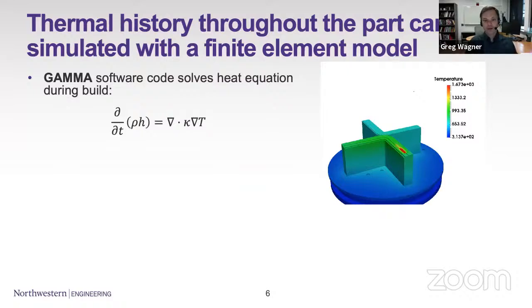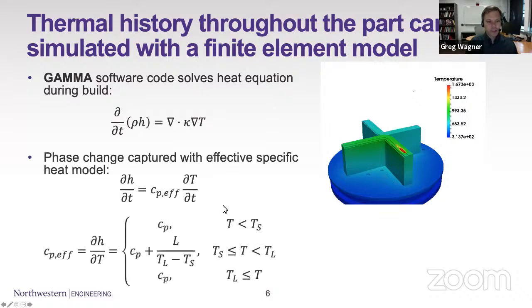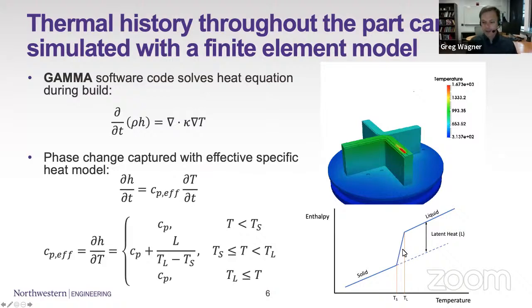As material gets added, of course, the complexities in the simulation are that you change your boundaries and you're activating elements and things like that. But a lot of this turns out to be bookkeeping. The formulation that we're using in this case is an effective specific heat model. So we're capturing the latent heat, but we're capturing it through a modified specific heat that has this kind of smeared out jump condition across the solidification of the liquid, the solidus to liquidus region.